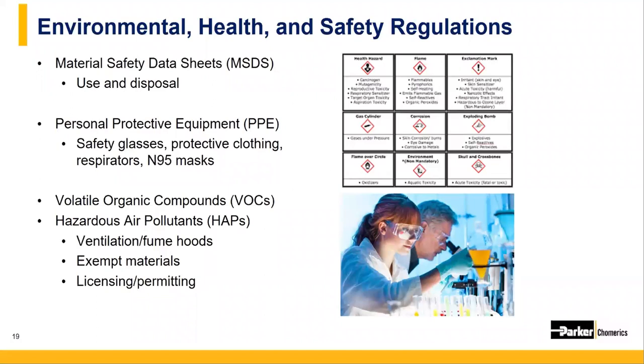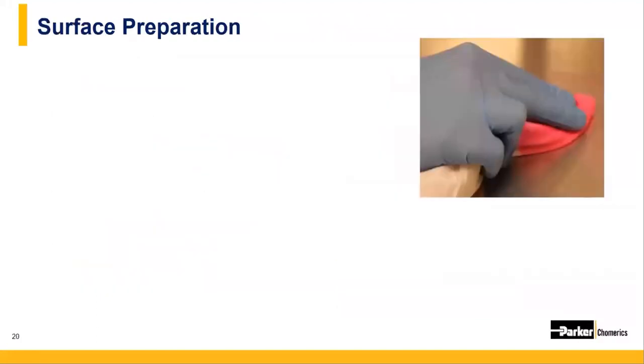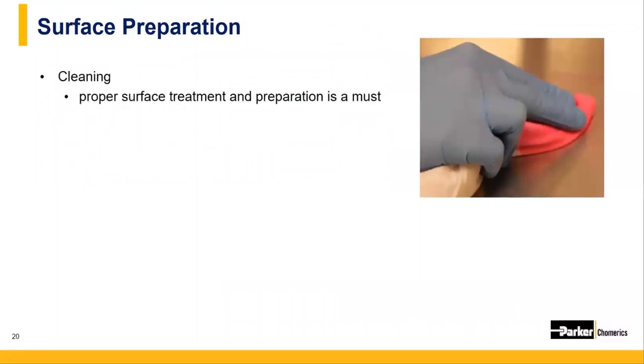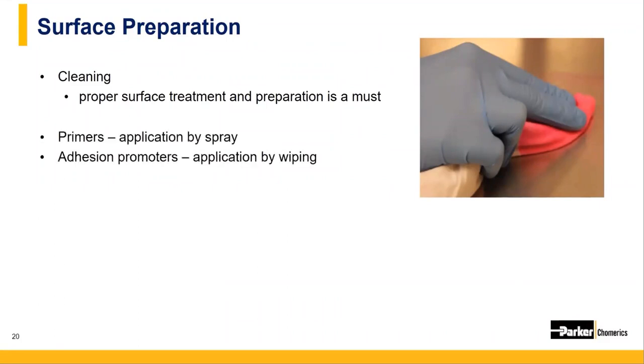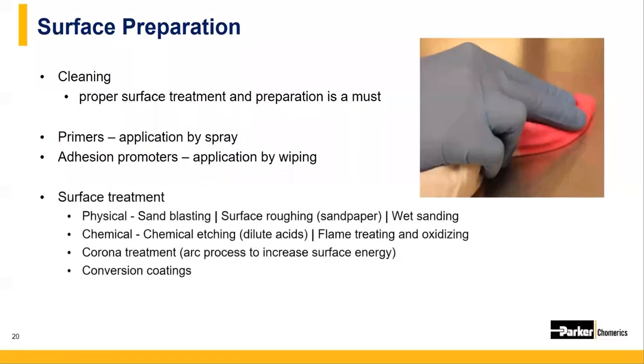In many cases, licenses or permitting may be required for organizations that are dispensing coatings and releasing large amounts of VOCs. And of course, before any coating is applied, there are several steps to take when preparing the surface. At the very least, you need to clean the surface and keep it free of any oils, dust, and dirt. Just like with conductive sealants and adhesives, primers and adhesion promoters can be used to provide the best adhesive properties. The important difference between adhesion promoters and primers is the application method. In general, primers are sprayed onto a surface, while adhesion promoters are typically wiped on with a clean cloth. Surfaces may need to be physically roughed or chemically etched so the materials adhere well.